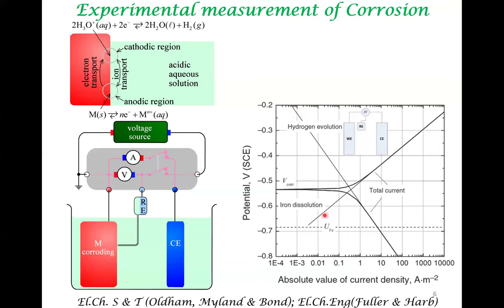And what is shown here are two lines corresponding to iron dissolution, the relevant anodic reaction, and the cathodic reaction is also presented, which is the hydrogen evolution reaction that is indicated by the straight line. And here we are also representing the total current. Okay, so as the potential changes in the anodic manner and the cathodic manner above and below the corrosion potential, the total current also changes. And how can you perform such changes is by imposition of external voltage and external current in this setup.